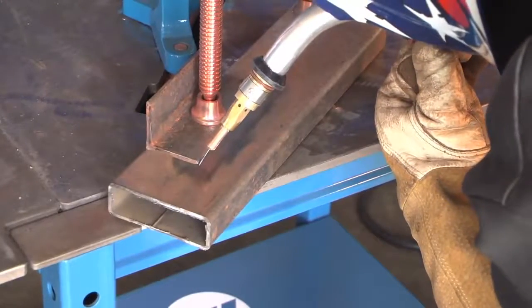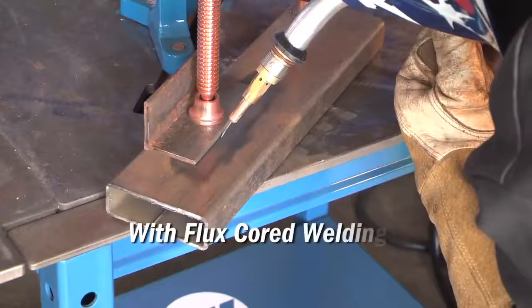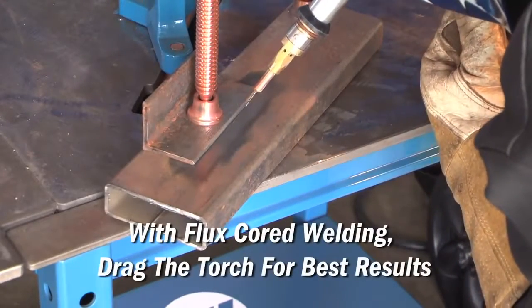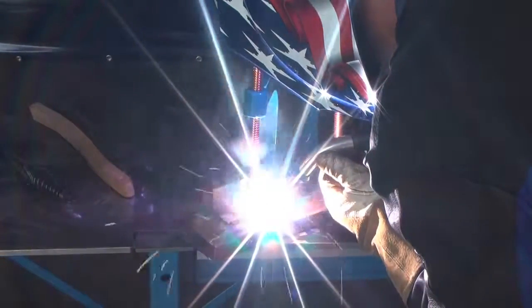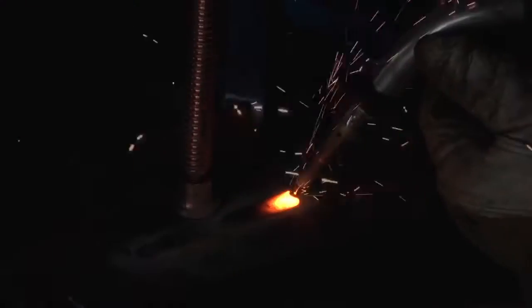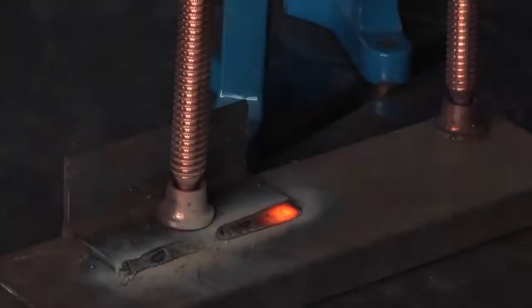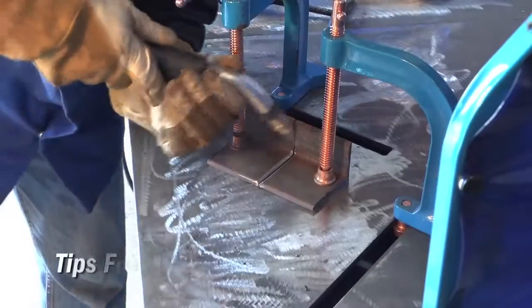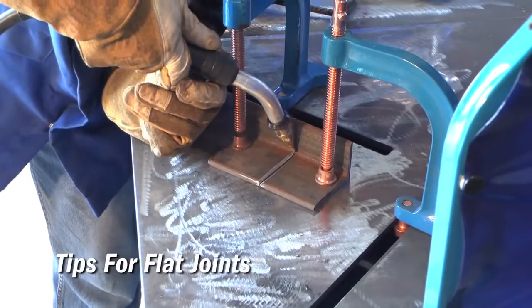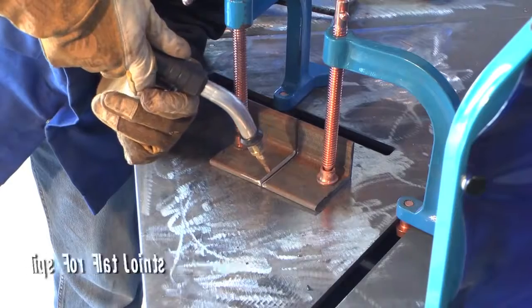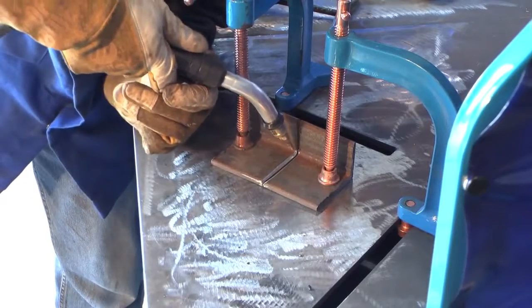Gun travel for flux core varies a little bit differently. Instead of pushing the gun forward, what you'll need to do is drag the gun or backhand weld, similar to stick welding. For a typical butt weld or flat position weld, your gun should be at 90 degrees to your workpiece and 10 degrees tilted back, welding with a slight weave, pausing side to side to avoid undercut.